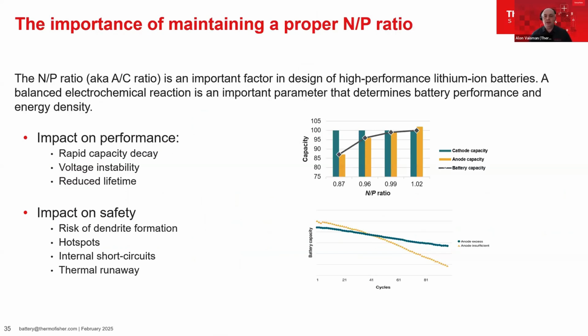Ensuring the uniformity of the active material loading during the electrode coating process is one of the most critical quality parameters. When the anode and the cathode come together in the assembled cell, the ratio of anode to cathode charge capacity, A to C ratio or N to P ratio, will determine the electrochemical balance and will affect the performance of the cell. Anode to cathode balance needs to be maintained locally at each point over the entire electrode area, not just as an average.